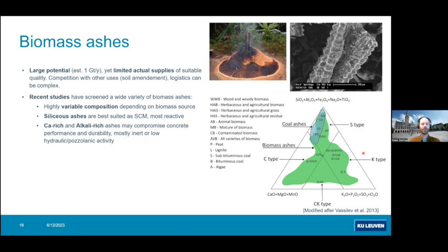On a material level, what's known from recent studies, and it's actually confirmed across a wide range of biomass ashes, is that depending on the biomass source, whether it's herbaceous or woody or animal, you really have very different ash compositions. So you really have to be careful about what materials you're taking in and what the sources of biomass are.